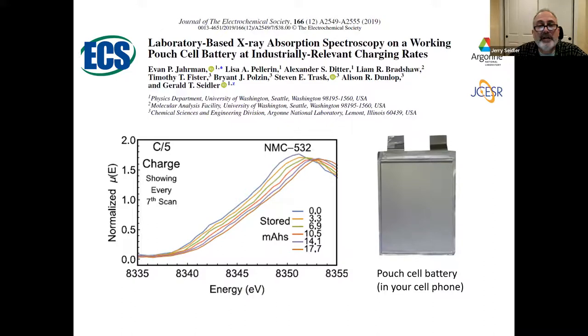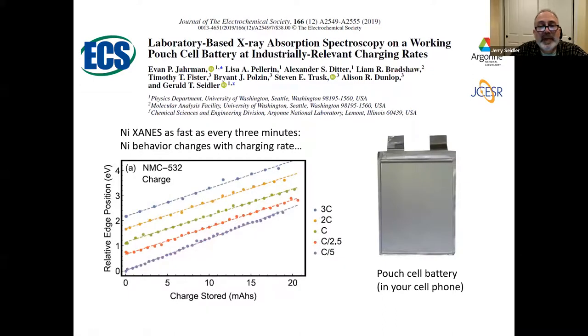We've done some in situ work on batteries, doing rapid cycling, even with an earlier generation of instrument. And this is, I believe, the nickel K edge, showing the shift in nickel with charge state. And indeed, at various different charge states, the edge position behaves in different ways, depending on the amount of charge stored. And we're able then to do the nickel XANES about every 3 minutes. And that's old optics and a slow detector. The newer instruments using the same overall layout can do the same thing in 10 or 20 seconds.